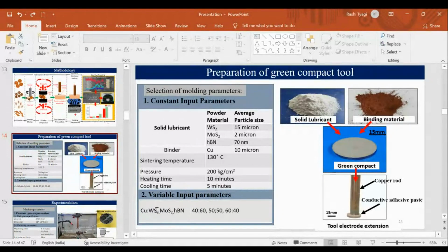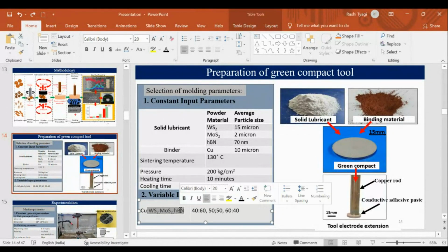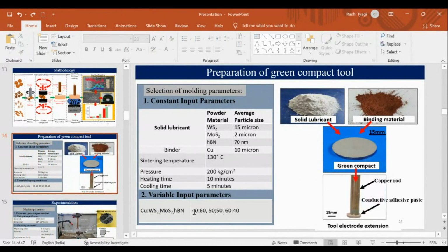This is a variable process parameter, the mixing ratio. We are varying this mixing ratio because we are using the powder in different ratios, such as if 40% is copper, then WS2 will be 60%. If we are using copper 50%, then MoS2 will be 50%. If we are using copper, then hBN is 40%. So these are the three mixing ratios that we are utilizing for particular combinations to form the experiments, which I will also show you in the experimental table.